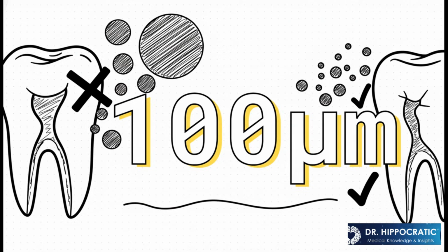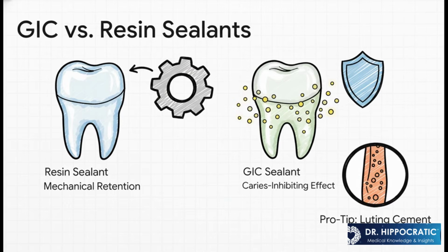The pits and fissures on our back teeth are incredibly narrow, and the glass particles in the early GICs were just too big. They couldn't flow into any fissure that was narrower than 100 micrometers, so that meant they couldn't seal the very areas that were most at risk for decay. So you might be thinking, if resin sealants stick better mechanically, why would we even bother using GIC for sealants? Well, the answer lies in GIC's chemical superpower, its incredible caries inhibiting effect. The fluoride that it releases doesn't just sit there, it actively gets incorporated into the surrounding enamel, making it way more resistant to decay.